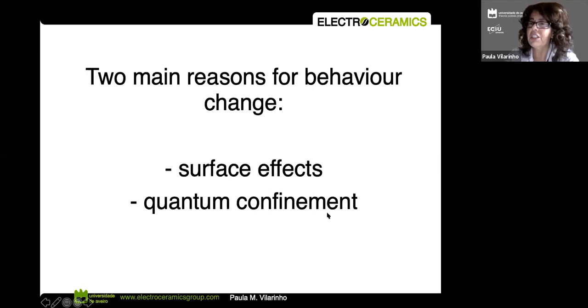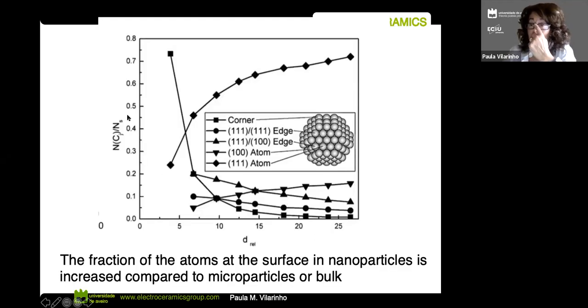Quantum confinement is very well observed in semiconductor quantum dots. So here I have an example that I like to show that is associated with really what is happening when we decrease the size. The fraction of the atoms at the surface in nanoparticles is increased when we decrease the size compared with the microparticles. So this means that we have much more atoms in the surface, than the ratio between surface and volume. So this means that the surface starts to play a role. And in terms of engineering, this is really very, very relevant. And I think many industries already perceive that. And I'm not going to give you too many examples of the benefits of nanotechnology, but they are already in use for some time.